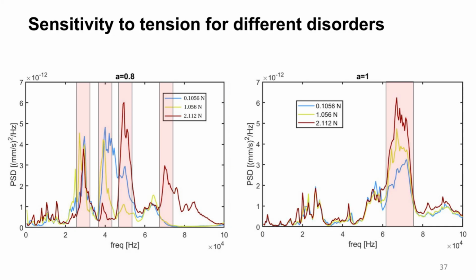For higher perturbation of 1, which is the maximum perturbation that has been tried on these metamaterials, the peaks seem to realign with 63 kilohertz frequency, which is the same frequency at which the Bragg peak originally appeared. And while this does have dependence on tension, it's not as extreme as seen in the original unperturbed ordered lattice.